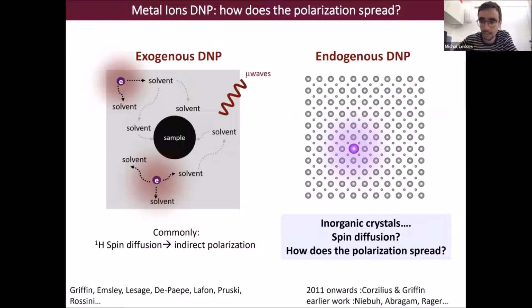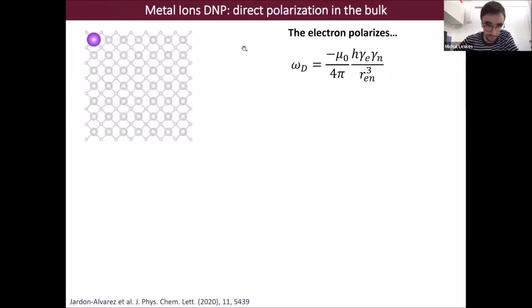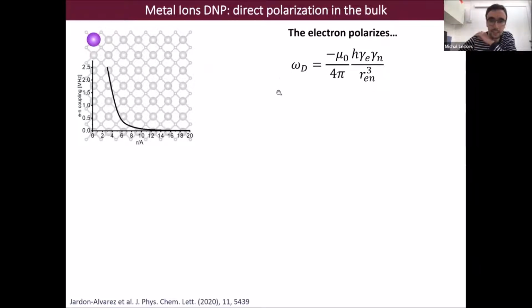So in order to answer this question, we need to look at the relevant interactions for this DNP process. The most important interaction is the dipole coupling between the unpaired electron, the metal ion that we introduced, and the nucleus of interest that we are going to hyperpolarize. And the dipole coupling, of course, depends on the inverse of the distance to the power of 3. So the farther away a nucleus is from the metal ion, the weaker the dipole coupling, and consequently, the less efficient will be the polarization. But at the same time, we have to keep in mind that in these rigid inorganic solids, relaxation times can be very, very long, to a point where the metal ions that we introduce for DNP purposes are at the same time the main source of relaxation.